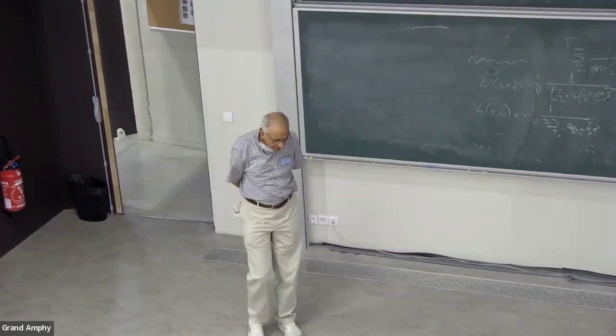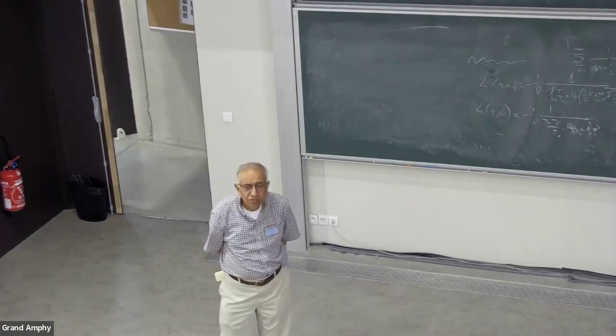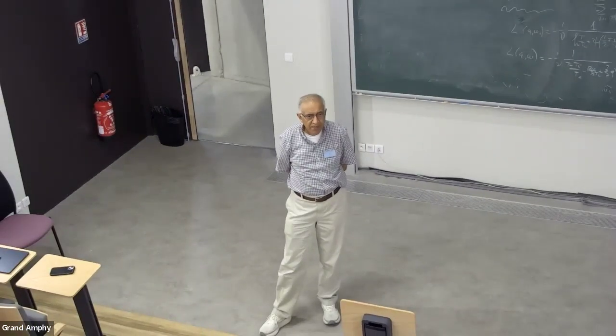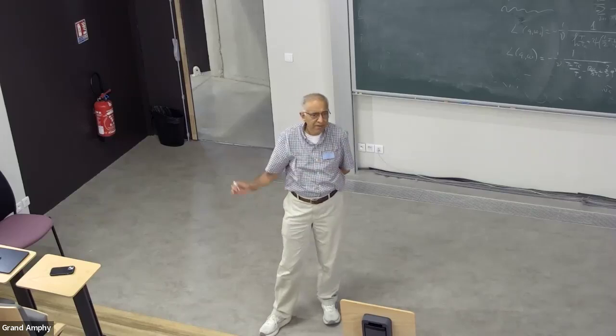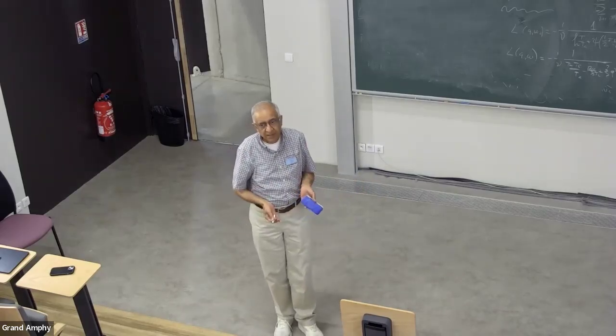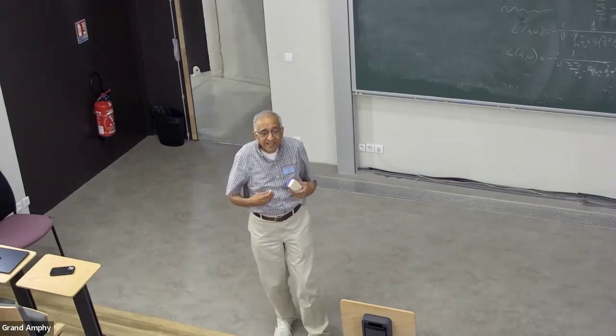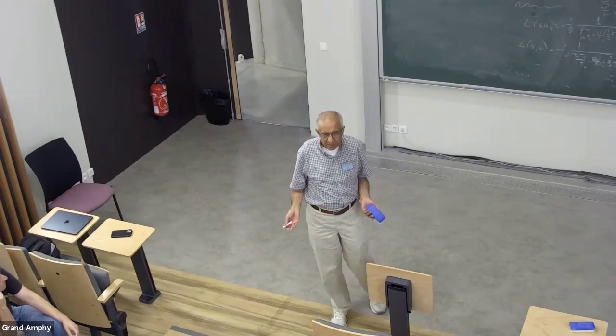So the first statement is that, did you know that the Anderson insulator is a gapless insulator? Yeah, okay. So it has a continuous spectrum. It's not like a band insulator or a Mott insulator or something. It's gapless. Normally you think gapless systems are metals. The Anderson insulator is not a metal because the states near the chemical potential are localized. In fact, in 2D, all states are localized. So no matter where you put the chemical potential, they're localized.